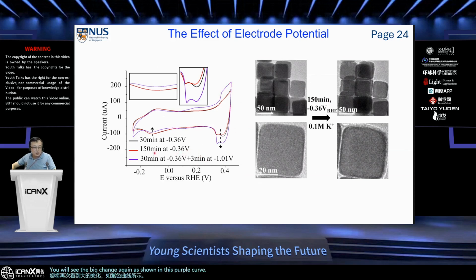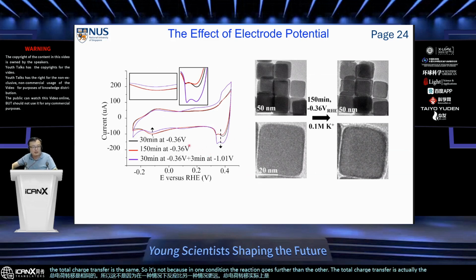And notice that for these two processes, 150 minutes at -0.36 volt and 3 minutes at -1 volt, the total charge transfer is the same. So it's not because in one condition the reaction goes further than the other. The total charge transfer is actually the same. So it's actually a different process going on.